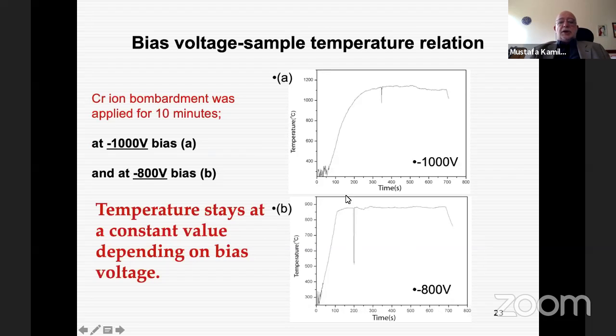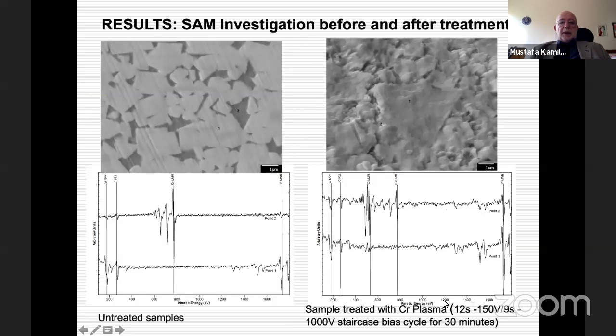And here you see how effectively we can increase the temperature of our substrates by using in-time ratios of seconds. We can increase up to 1,100 degrees. We can increase to 850 degrees. And we can tune this temperature by changing the bias voltage. And then after application of this method, we characterize the surface of our coating materials, tungsten carbide cobalt.